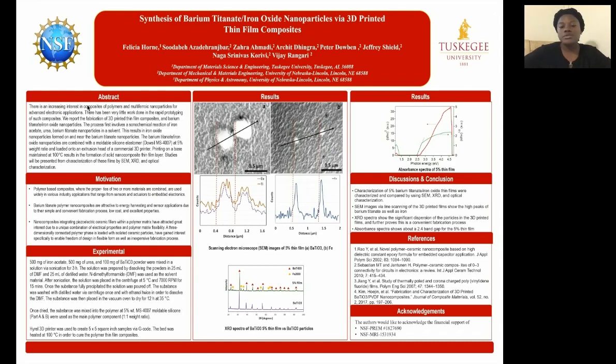So with XRD, we wanted to ensure that the elements within this thin film were what we said we put in them. So we're looking for the barium titanate. We're looking for iron oxide as well. So if you can see for the XRD spectra, we basically paired it up against a barium titanate spectra that was already in the system, and we have the exact same peak. So the barium titanate was again commercially purchased, so we know that's there, but we just wanted to still make sure that it was in that matrix. So also the iron oxide, you see the iron oxide peaks there as well. So we were able to find that out via XRD, and the same with SEM.